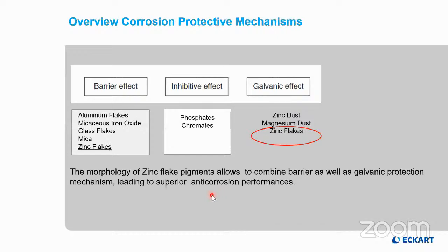Corrosion as such occurs through 3 different mechanisms. The first one is an inhibitive effect, which is typically provided by species like phosphates and chromates, and there is a large variety of different products available in that industry. This inhibitive effect is not used when using zinc, both zinc dust and zinc flakes. For zinc flake and zinc dust pigments, a galvanic effect is provided and also a barrier effect. These 2 effects contribute to the corrosion protective performance of zinc flakes.